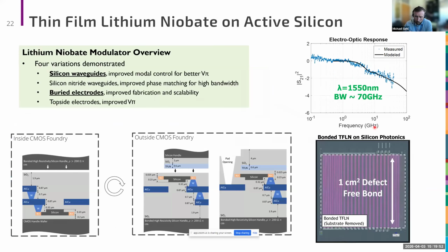And so in order to make this compatible with our full silicon photonics process, we've expanded on this idea a bit more, and you can see the process we use now highlighted on the bottom. We begin with a very thin buried oxide SOI material. We fabricate our silicon photonics as normal, but then we bond a new handle wafer onto the top of that, still at the full 8-inch wafer level.